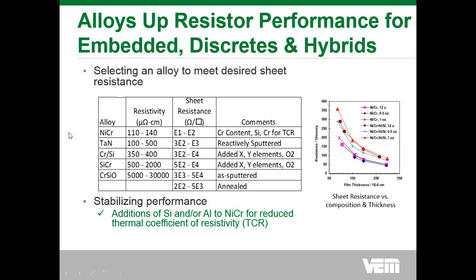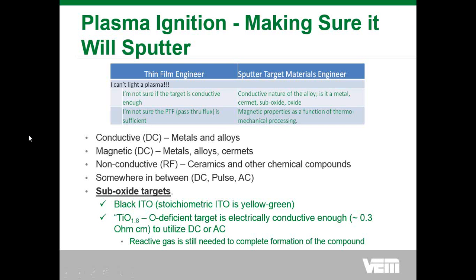Another example, titanium dioxide. The one example I'm referring to utilizes a titanium oxide, not TiO2, but TiO1.8. The oxygen deficiency in that improves the electrical conductivity sufficiently so that you don't have to use RF rectification, but you can use DC, pulse DC, or AC type rectification. However, if you're trying to get a TiO2 film, you're still going to need to bleed in a reactive gas such as oxygen to get a stoichiometric film.